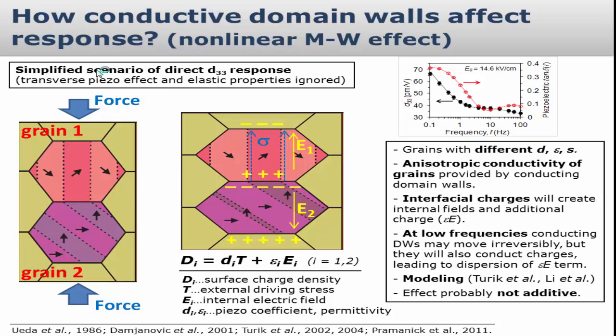And this can happen, for example, because we have conductive domain walls. So this term can also become dissipative. You can get a relaxation in this term, and since these two couple, you will get this huge phase angle in the piezoelectric behavior at low frequency. Basically, the coupling between conductivity and piezoelectric response comes from the fact that in these materials you always have electromechanical coupling, and this conductivity can make a dispersion in the dielectric term, which will be transferred to the electromechanical behavior. This is how we think this specific effect can be explained in BiFeO.